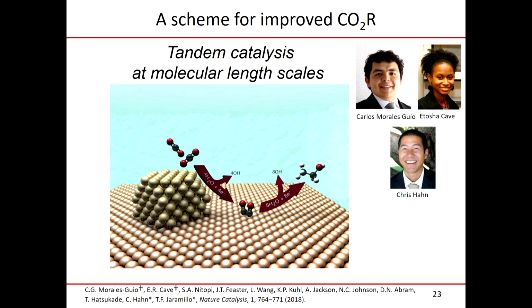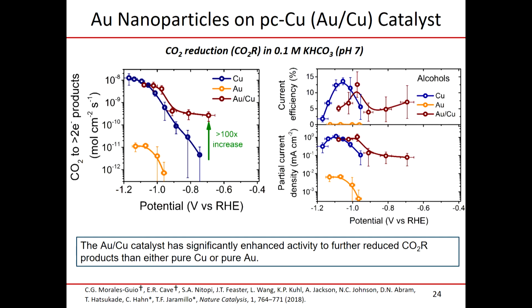And this was our scheme. It's really a tandem catalysis scheme at molecular length scales, with the idea that you can flow in your CO2 in neutral, have the gold make your CO and create an overpressure of CO on top of that copper, which can then do the CC coupling to take it forward, and it works.